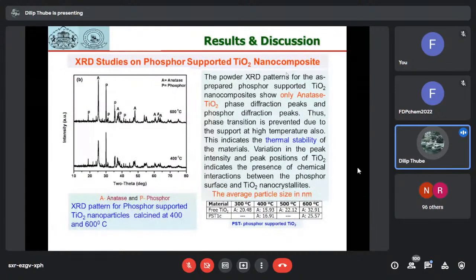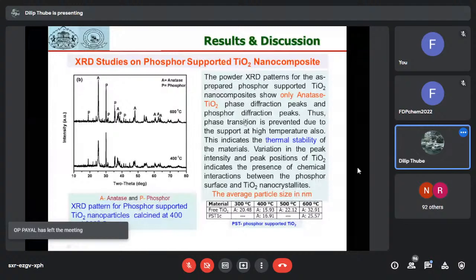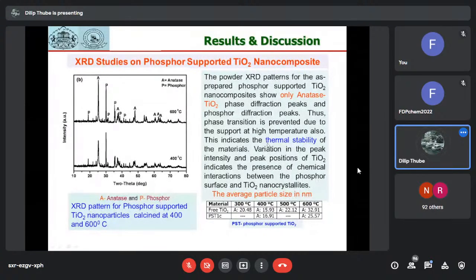In the previous slide, we saw XRD of pure TiO2 materials, whereas this slide shows XRD of phosphor supported TiO2 nanoparticles. The most important thing is that if you sinter at about 600 degrees Celsius, there is no evidence of the rutile phase. That means because of the presence of the phosphor material, TiO2 nanoparticles remain exclusively in the anatase phase, and that is very important. Therefore, the advantage of this phosphor support is that it gives thermal stability to the material.